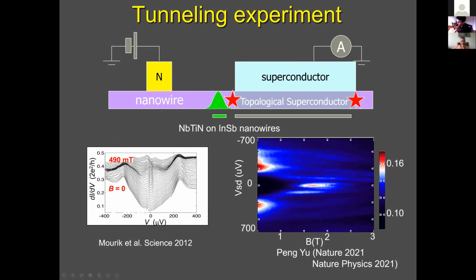So we have 4 ingredients in our recipe, and they are the nanowire with spin orbit, and there is magnetic field on, and the superconductor is just physically put on top of the wire, and it induces, by Andreev reflection, superconducting correlations between those electrons and holes in a non-superconducting material, which is a nanowire. And so the entire topological physics takes place next to a superconductor in the induced superconductivity regime, which is labeled topological superconductor on the screen.